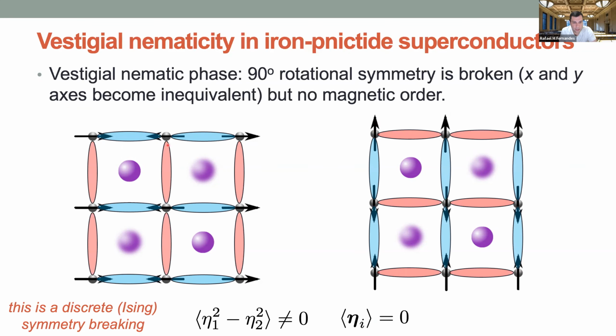You can see that what it means is that I can write down this order parameter, eta1 squared minus eta2 squared. When it's non-zero, it means fluctuations are different along the X and Y directions, and they break the 90-degree rotational symmetry. I can do that even though there's no long-range magnetic order. Another way to think about this is that these spins are not ordered, but they are fluctuating in a way that these 2 are locked to fluctuate in an anti-parallel fashion, and these 2 are locked to fluctuate parallel to each other. So it's still fluctuations, but they break a symmetry.